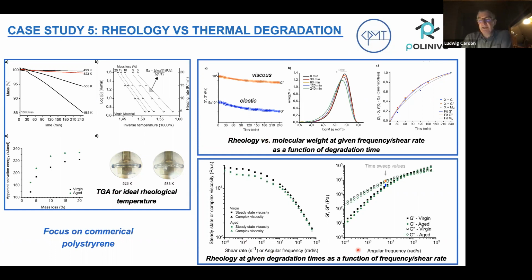Well, when we investigate this one, as you can see, the G prime, G double prime for virgin and for aged materials, this is very important for us in the scope of either standard extrusion processing or, let's say, the extrusion-based 3D printing. To know the lifetime or the residence time of your polymer inside your extruder, and to try to redesign extruders so that the residence time is not too high or the shear effect inside your extruder is not too high, and to avoid degradation during your polymer processing.